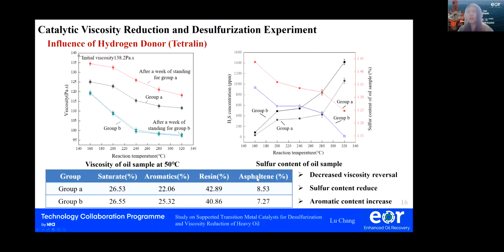Then we test the catalyst desulfurization and the viscosity reduction performance from 4 aspects. The first one is the influence of the hydrogen donor. Tetralin is added as a hydrogen donor here. The first graph shows the viscosity of the oil sample at 50 degrees centigrade after reaction at different temperatures. Group A has no hydrogen donor added, while group B has hydrogen donor added.